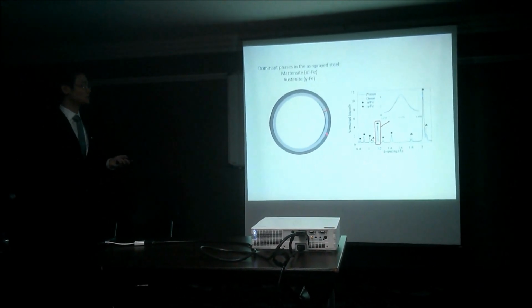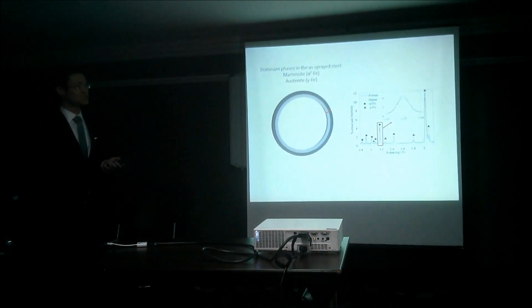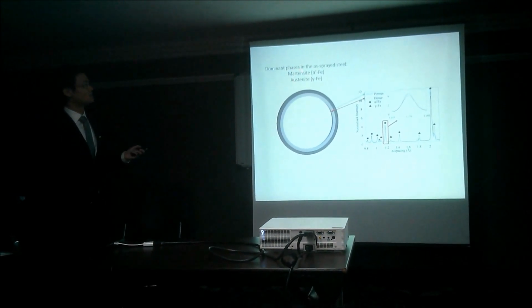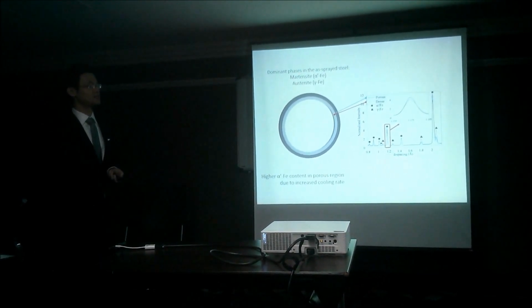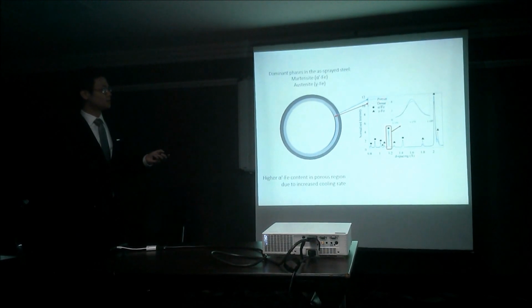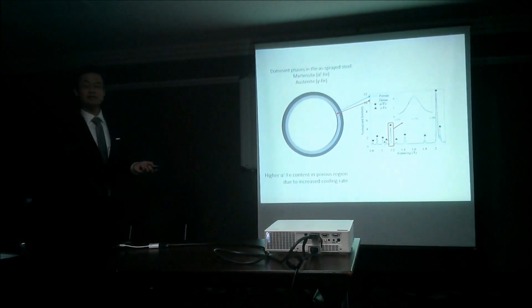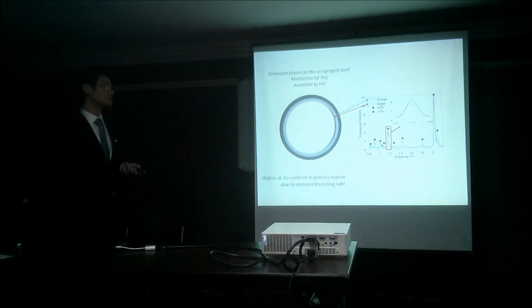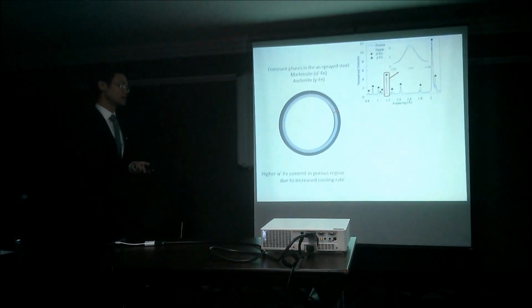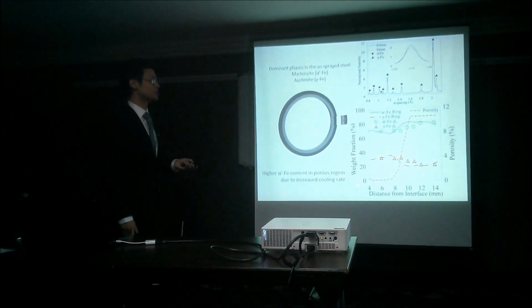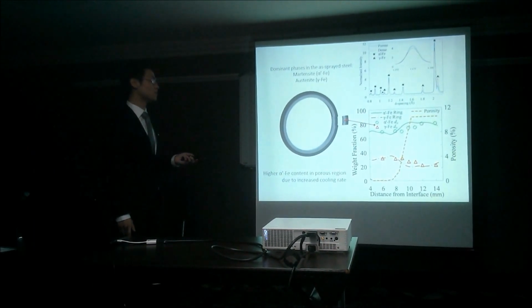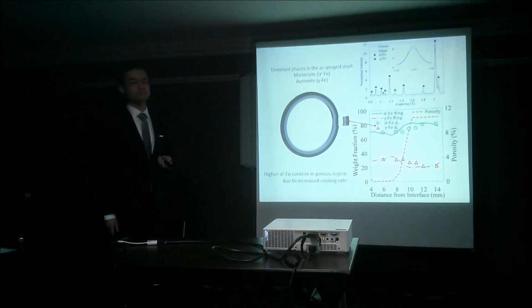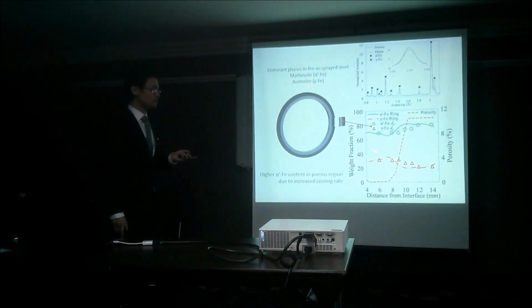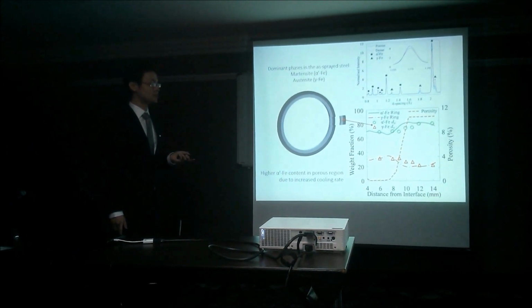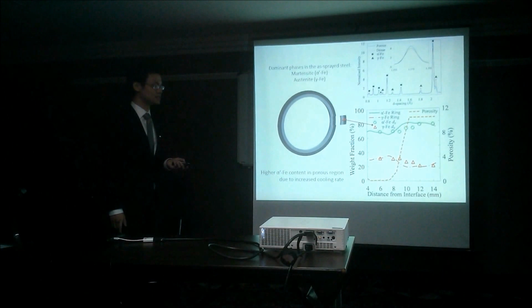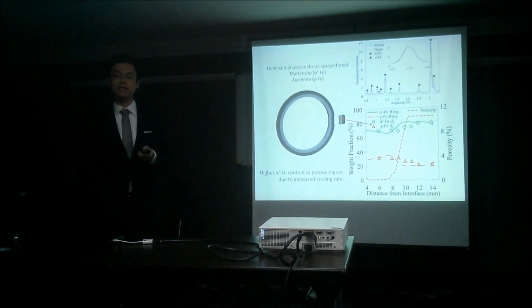So from our diffraction results across the ring thickness, we managed to identify martensite and austenite as our main phases in our sprayed steel. Now at the porous region, we managed to pick up higher martensite content due to the higher cooling rate. We then quantified the phase weight fraction distribution across the thickness of the sample for the stress-free and the ring sample. We can then use this phase weight fraction distribution across the interface, the distance from the interface, to help explain the stress development in our sprayed steel.